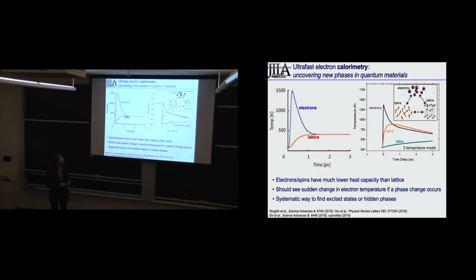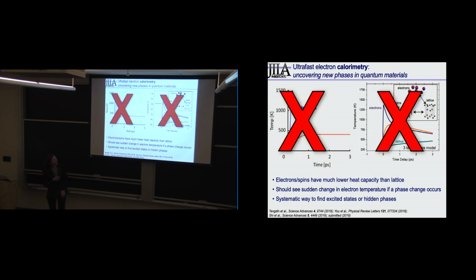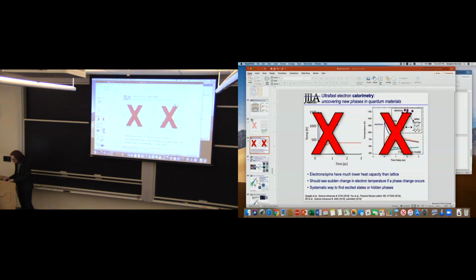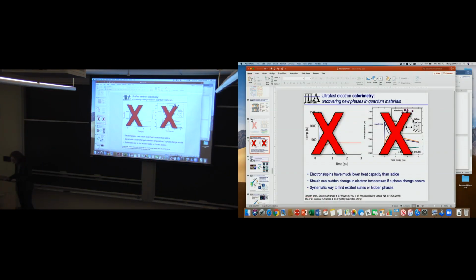Okay, so in other words, the 2 temperature model for CDW materials and the 3 temperature model for magnetic materials, you have to take them with a grain of salt for these strongly coupled materials. And with that, I'm going to go to my concluding slide, and I'll have to get out of display mode to do that efficiently.